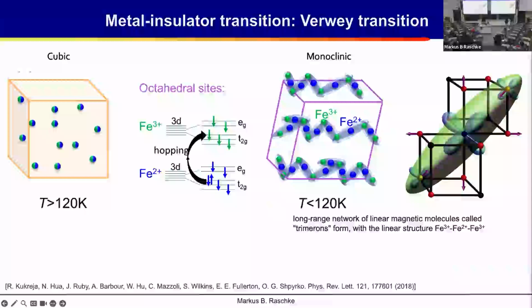Because now we need to couple these iron cations in a particular way so that the electronic orbitals overlap to form a metallic phase, but then also we want to decrease this overlap so that the electrons stay localized. This is part of this picture about conductivity, where we have electrons localized and they don't leave their site, and where we have electrons which would leave a site and then can percolate through the material.